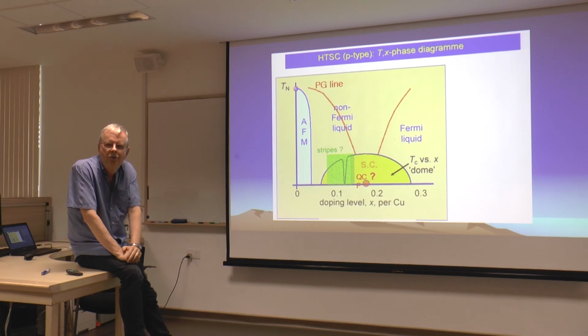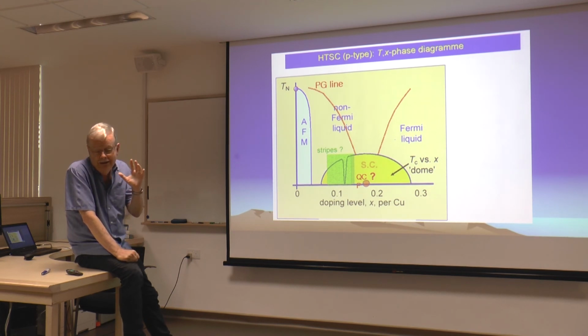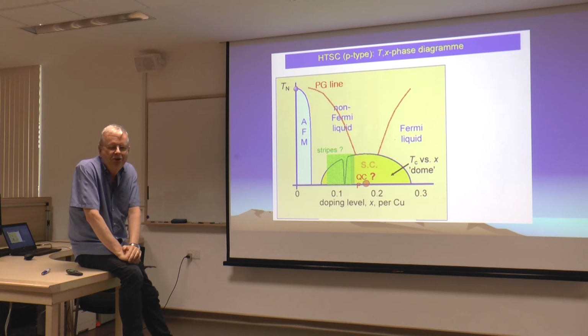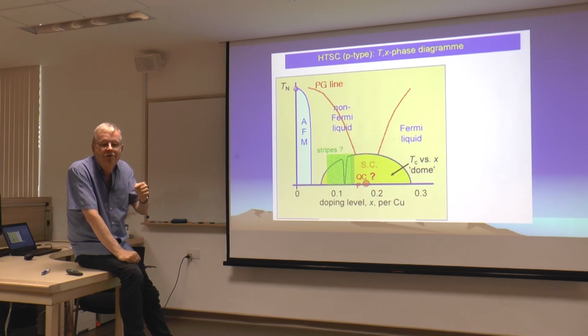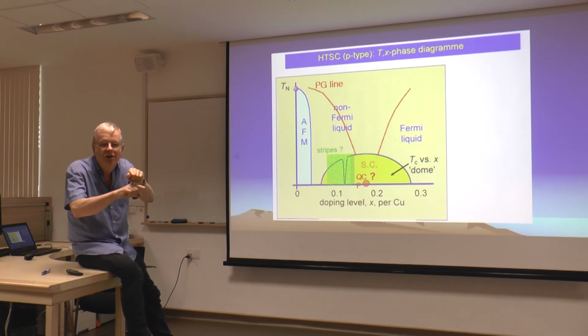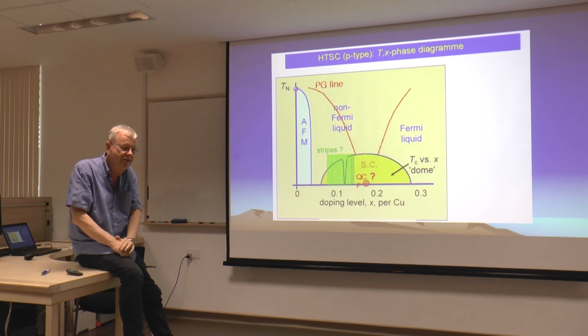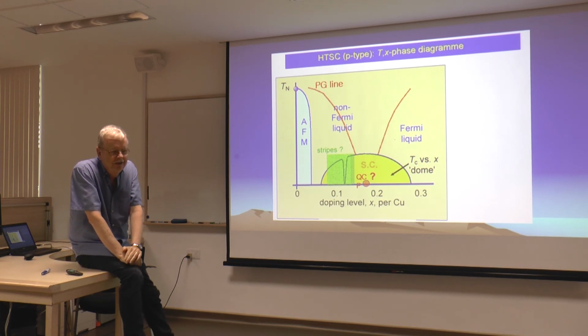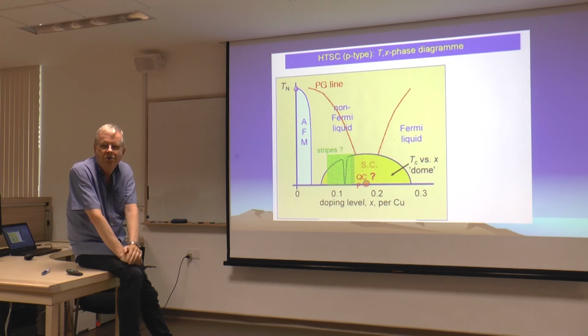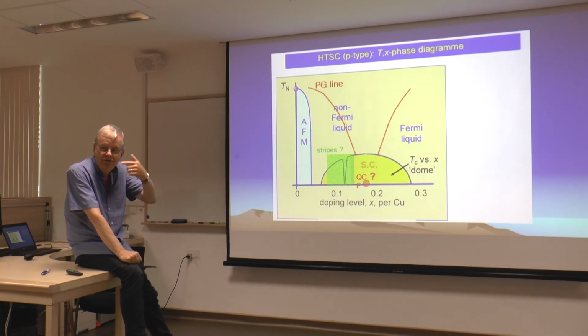Now this magnet has blown up once. It's very exciting. I've used it. I've measured specific heat in 100 Tesla. Very difficult, particularly if you're using a metal, because as you ramp the field up, you have all of these induced currents. Plus, there's something called the magnetocaloric effect. If the specific heat of your sample changes with field, it will move to a different temperature because you've changed the field. So we discovered lots of things. But they make you exit the building when the field pulses, and the field only pulses once an hour because you have to cool the wire down so you can run all that energy.